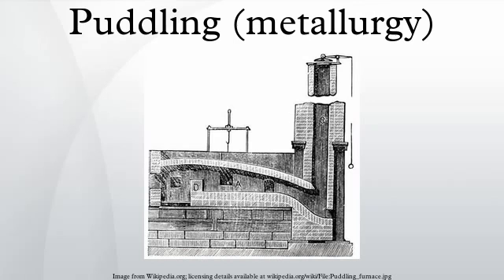Sometimes a large pair of tongs are used to remove the puddle balls. These puddle balls are then transported to the hammer or squeezer by dragging them along iron slopes built between the furnace and the shingling equipment, or more commonly the puddle balls are loaded into iron wheelbarrows and transported to their destination. Shingling expels slag and welds shut internal cracks, while breaking off chunks of impurities. The iron is then reheated and rolled out into flat bars or round rods using grooved rollers of successively decreasing size so that the bar is progressively reduced to the desired dimensions. Some of the iron oxide is from the scales that form in the later steps of shingling and rolling, and the quality may be improved by faggotting.